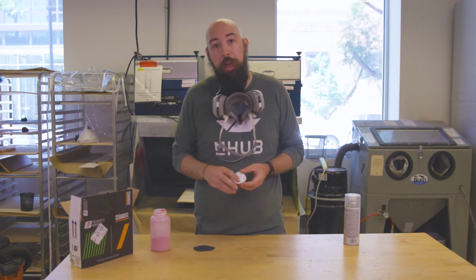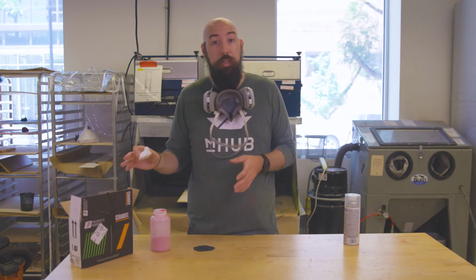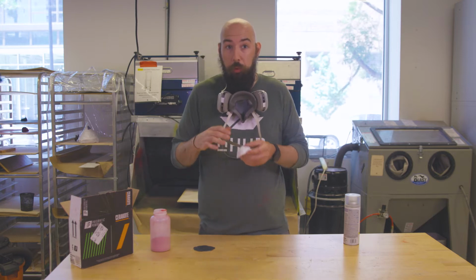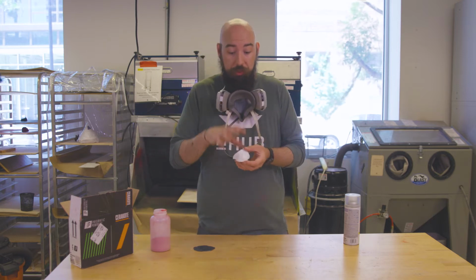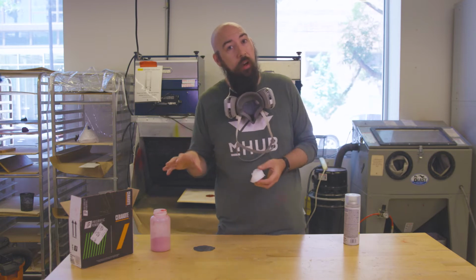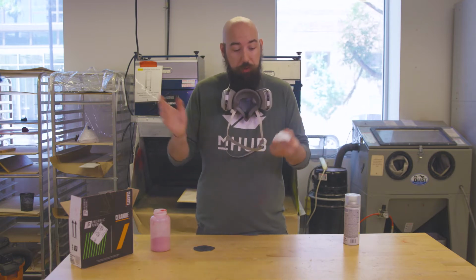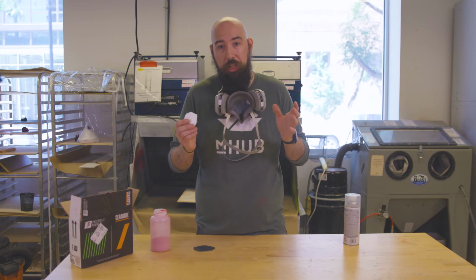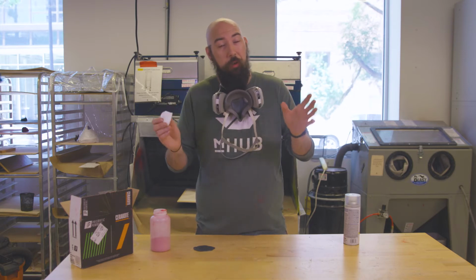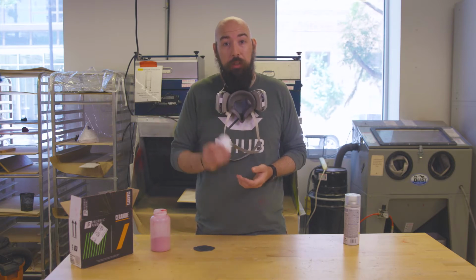We talked to Prismatic Powders to see if they had some of their powders that actually were within the range. So we're actually gonna bake this at 320, which is fairly low for powders, but it is totally acceptable for the nylon. Tested a bunch, melted a couple of parts, worked out fairly well. So let's go through that process.